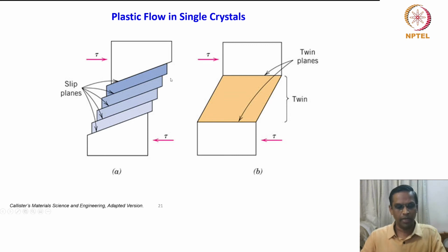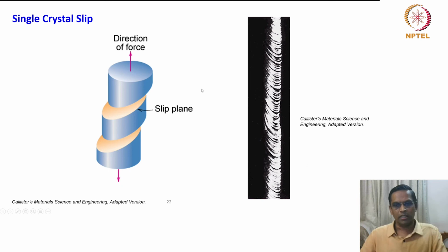So this is how the slip plane will look, and on the other hand, the other mechanism, twinning, will look like this. We will see the details in a few minutes. But what you see here is an untwinned plane, and these are twin planes, and in between you have the twinned region, and these are the shear stress directions. And this is a single crystal metallic sample, the real-time experiment given in this text. I just brought it to give an example of how the slip regions look exactly like what we have shown in this schematic.